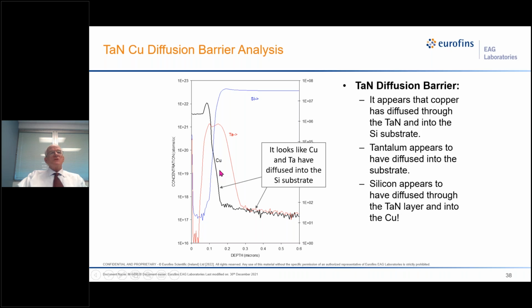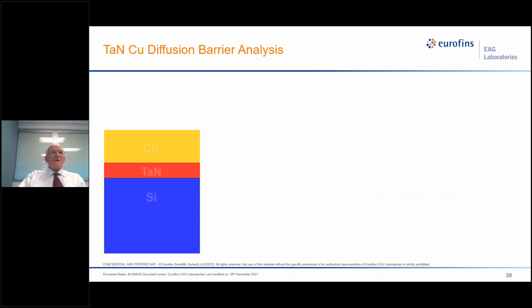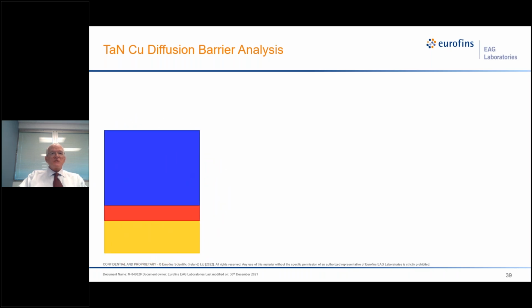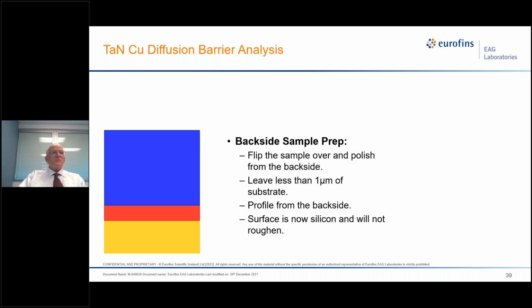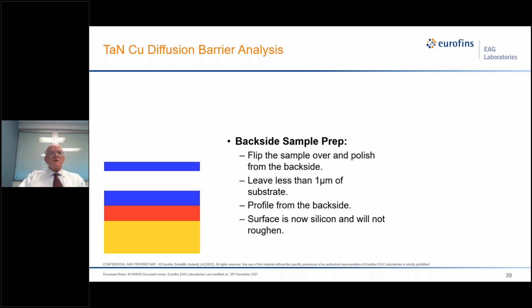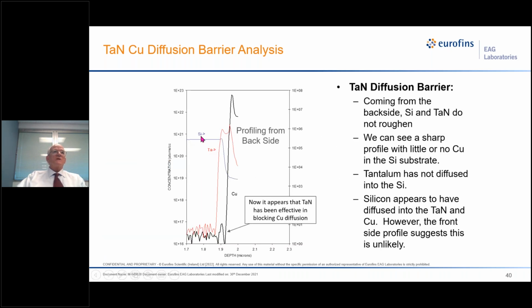And if you didn't do what I'm just going to show you in a second, you would have to mark those as artifacts. What can be done? We can simply turn the sample over, because silicon does not roughen when you sputter it, and you leave less than a micron of the backside silicon left by polishing it, and then you sputter through that with no roughening, and you get a beautiful profile here of silicon, tantalum, and copper. And you can see from this, where we have no roughening, the copper really has not gone into the silicon. The tantalum nitride has acted as a great copper diffusion barrier.